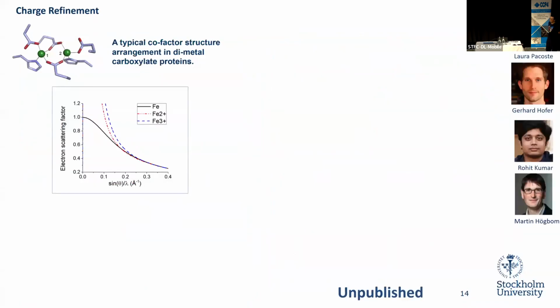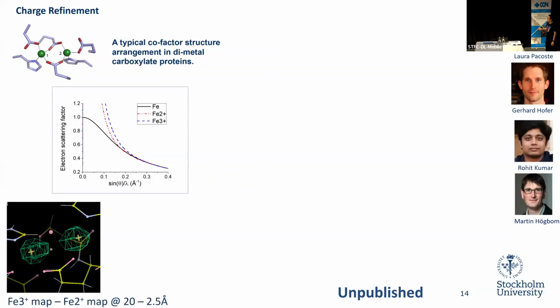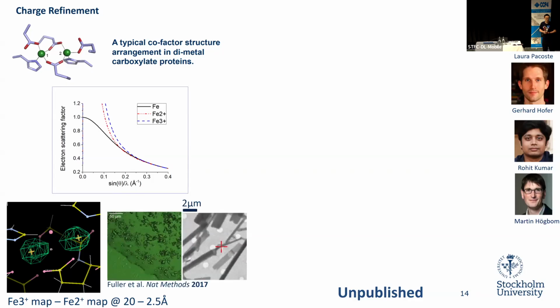This is one of the projects Laura has been working on, which is to refine the charge directly. In principle, as I said, the electron scattering factors of ions actually show quite large differences at low resolution range. So when she did the simulation, calculating the structure factors and then the electrostatic potential map from models with differently charged ions, in principle, with simulated data, we could see a huge difference between these charged ions. Right, and then the problem is whether we can collect data from them.